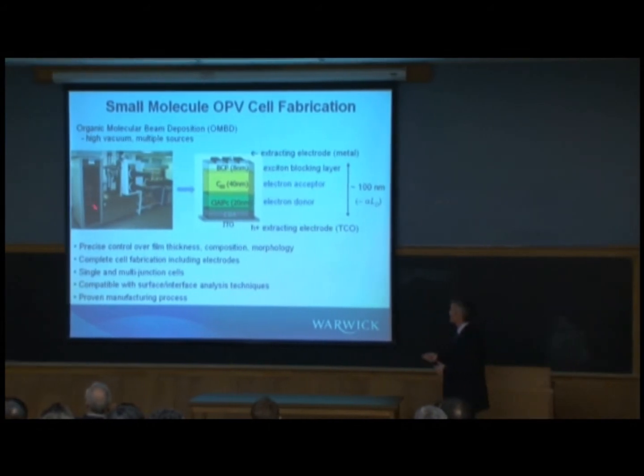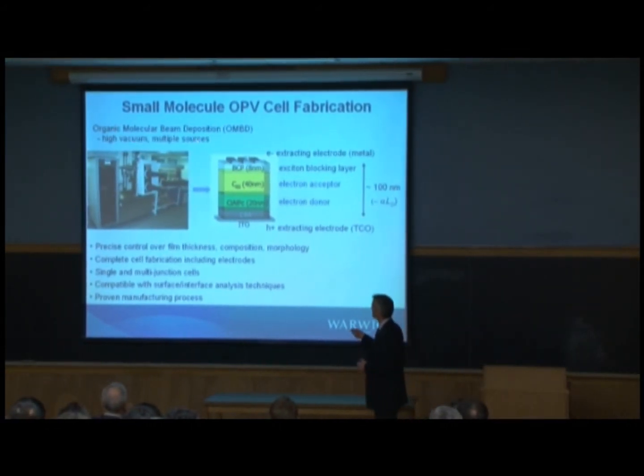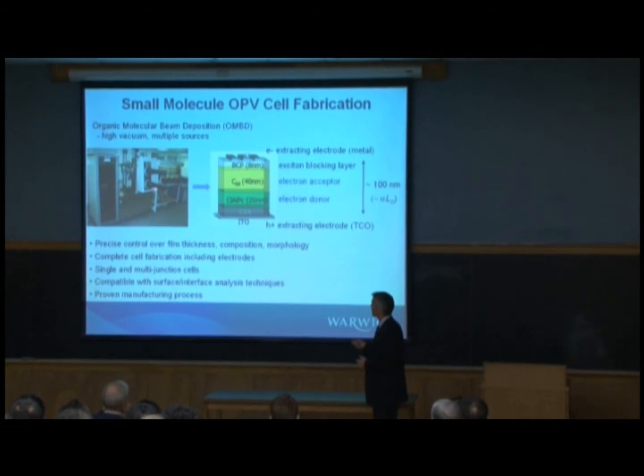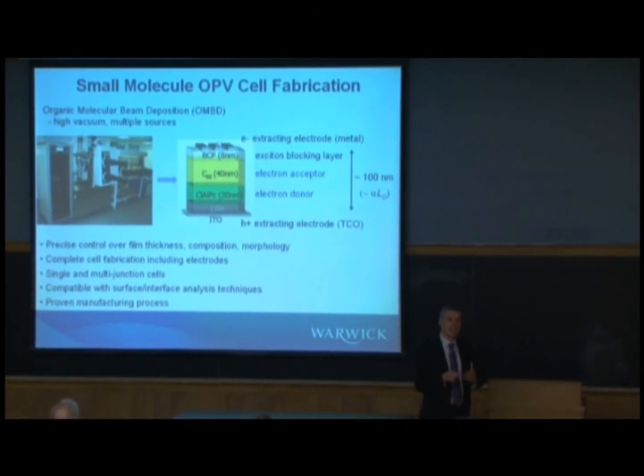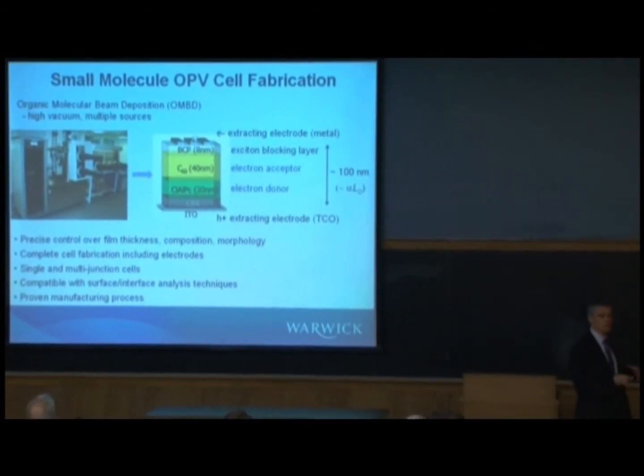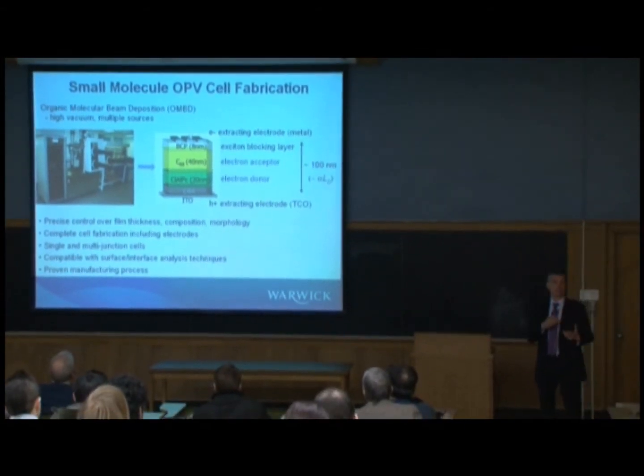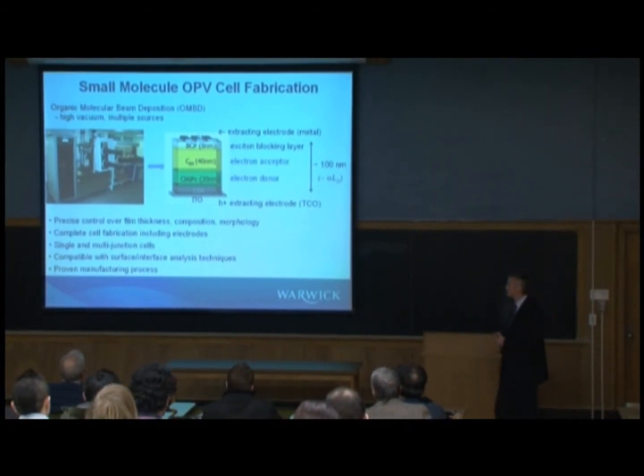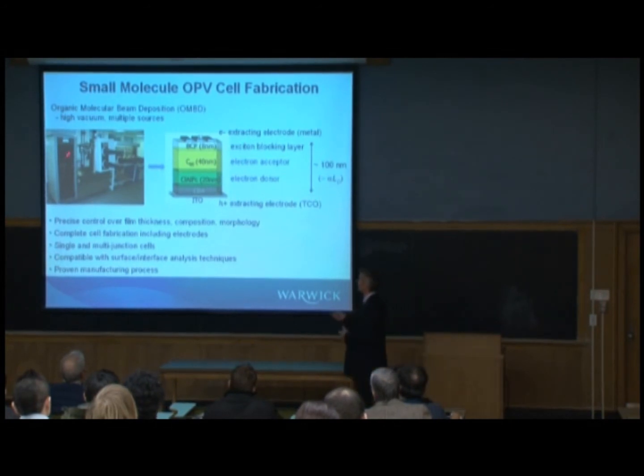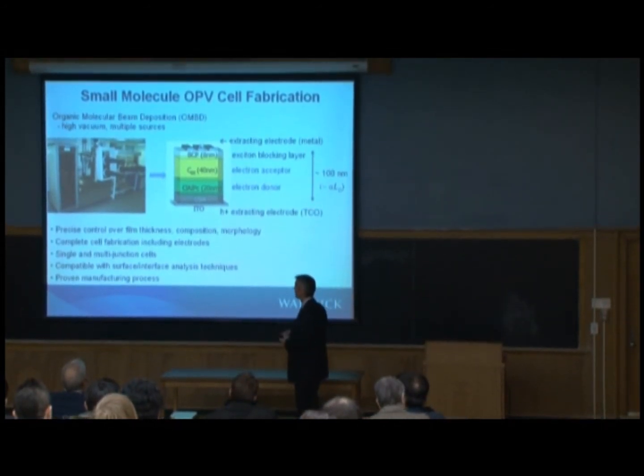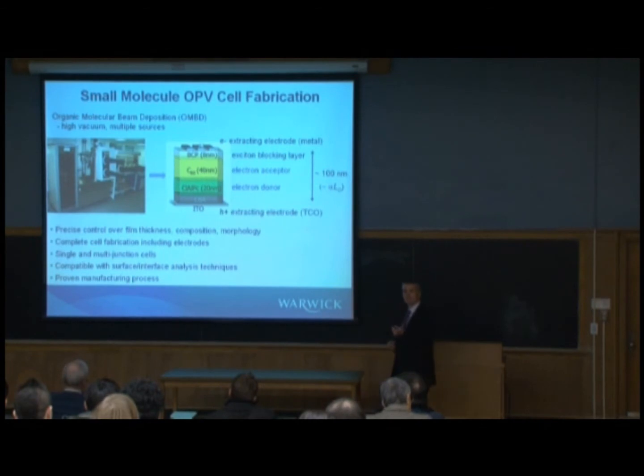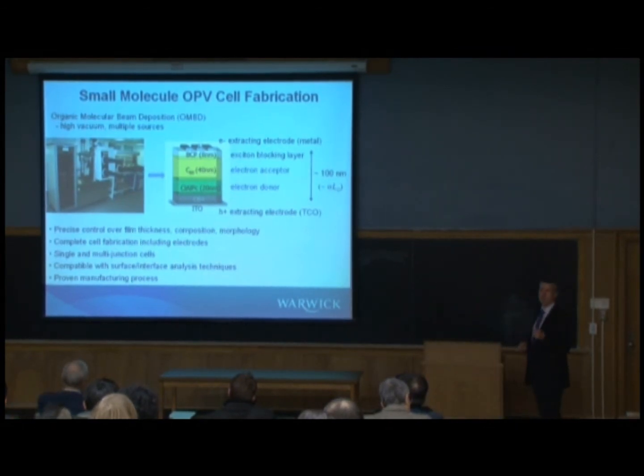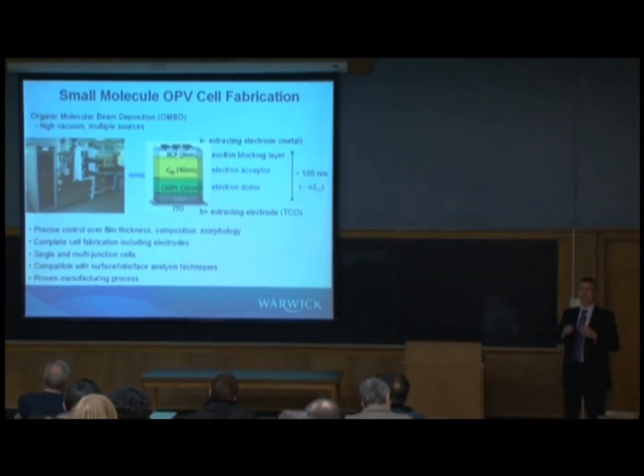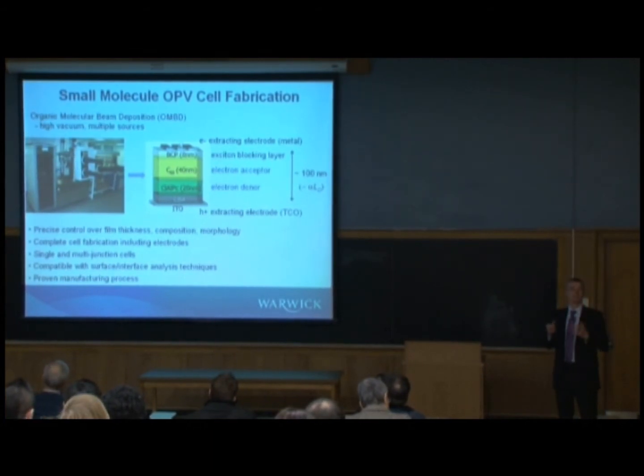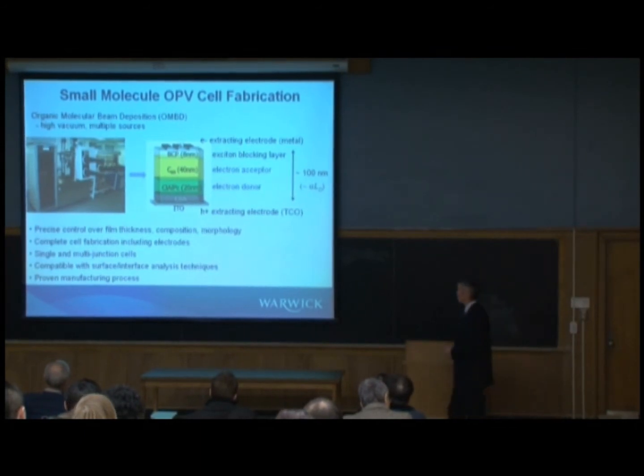These are fabricated in a system like this, organic molecular beam deposition. We've got two of these, typically around 10 or 12 sources within the chamber, so we can deposit a whole range of different organic, inorganic, or metallic materials within that system with a glove box and so forth. So it's a nice clean environment. These are materials that have sufficiently high vapor pressure that they can be evaporated without decomposition. So they can't be too big, the molecular weight is limited. You can't do this with polymers very easily, but you can certainly do it with small molecules.